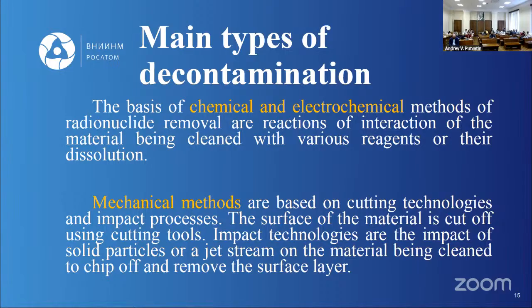But we can also use non-chemical methods. These are mechanical methods, based just on crushing of the surface, because as a result of mechanical attack on the surface, we can crush the contaminated surface, the contaminated layers also, and remove them from the metal surface.